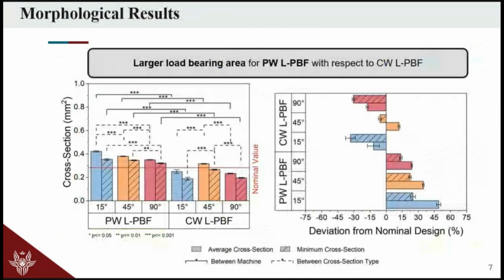But most importantly, we can compare the overall initial, preliminary at least, results of the printing. As you can see, the pulsed wave and the continuous wave laser powder bed fusion do not have only differences in between the different angles within the same technology, but there are critical differences also with respect to each type of manufacturing technology. In particular, you can see that there is an overestimation of the cross-section in the case of pulsed wave laser powder bed fusion, while there is an underestimation of the cross-section with respect to the nominal values for the continuous wave laser powder bed fusion, which in other terms means that the load-bearing area for pulsed wave laser powder bed fusion is larger than for continuous wave laser powder bed fusion.